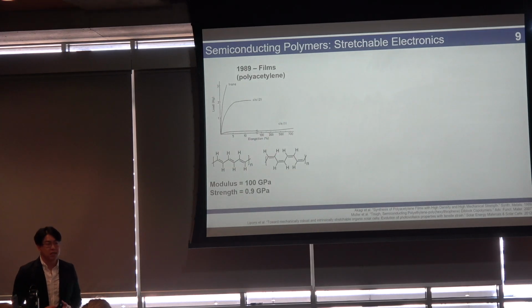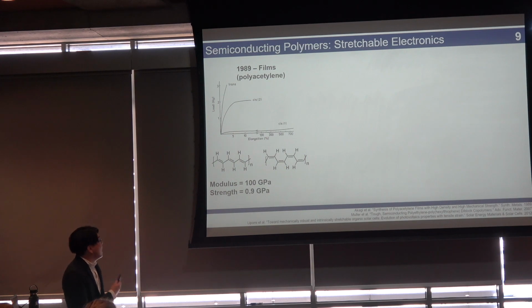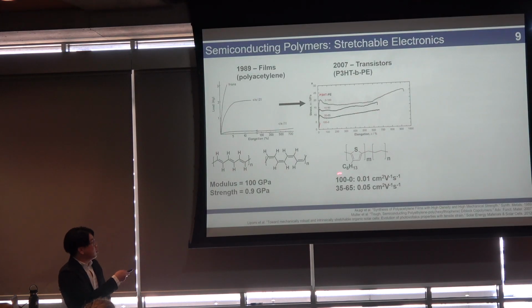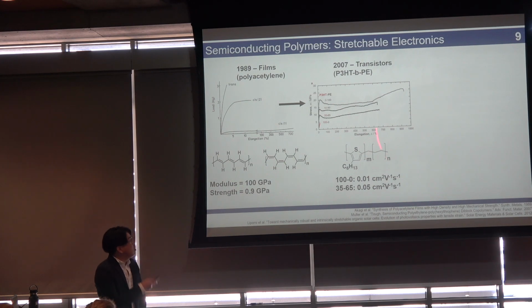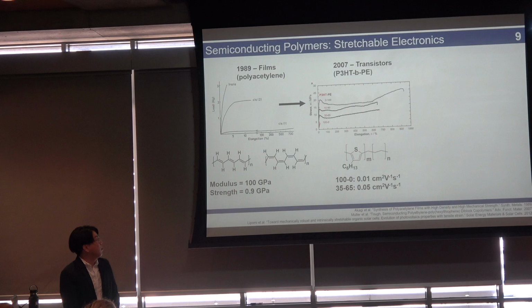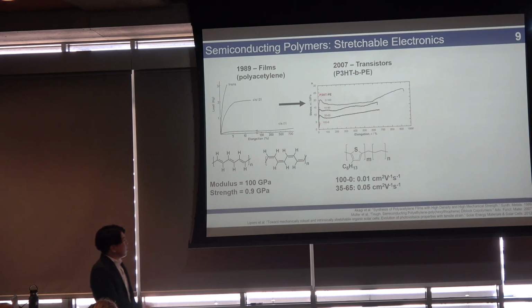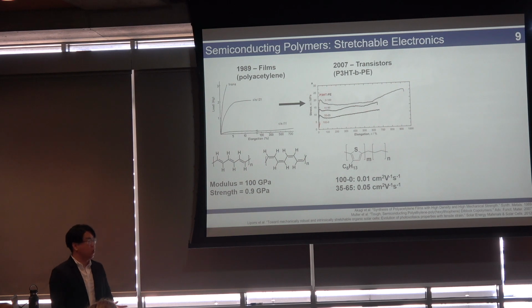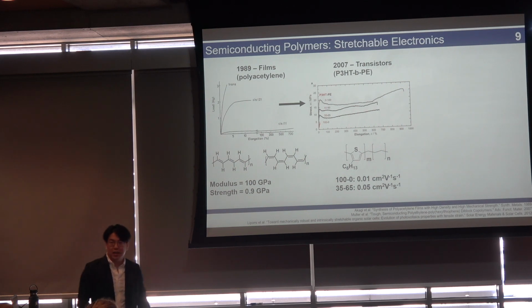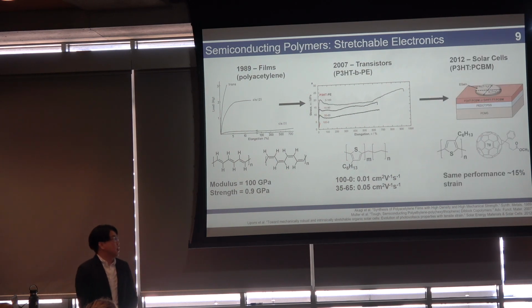And the interest in the mechanical properties of these polymers has changed over the years. In 1989, when we were still working with polyacetylene, people figured out that the trans form of polyacetylene is extremely strong and has very high modulus. This is basically comparable to modern Kevlar, so that's pretty impressive. But in 2007, a group figured out that you can actually co-polymerize P3HT over here with polyethylene, and you all of a sudden get a really, really stretchable polymer film. And not only that, even though you're adding 65% of an insulating portion, when you make transistors, your mobility is still higher than pure P3HT. So that's pretty interesting. And this concept was later applied to organic solar cells.